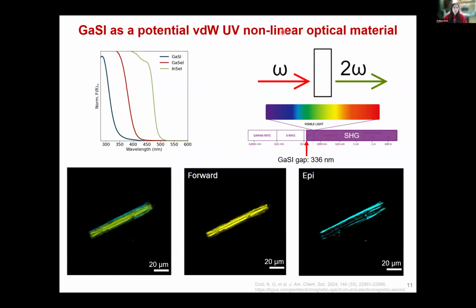We probed the second harmonic generation response of these materials, which is a nonlinear optical property in which 2 photons of an incident wavelength are combined within your crystal, and a photon at half the wavelength, or double the energy, is emitted. The band gap of gallium sulfur iodide is 3.69 eV, shown through diffuse reflectance spectroscopy, which equates to 336 nanometers, well in the UV region. So we can potentially do second harmonic generation into the deep UV using gallium sulfur iodide, and through SHG microscopy shown in these images, we do confirm the SHG response of gallium sulfur iodide.